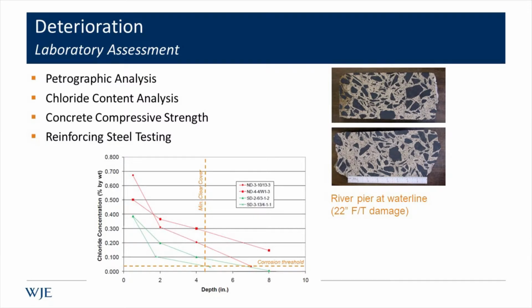That was followed up with a laboratory study where we petrographically examined some of the core samples to better understand the concrete and some of the distress that was present. We did chloride content analysis to figure out what the chloride levels were, and that's just one graph of one subset of cores. But generally what we found was the chloride concentration at the level of the steel was above the corrosion threshold. And that was the case even in areas where there was not distress. Concrete that looks sound and yet has chloride levels that are high enough to promote corrosion. And so that was something we needed to be mindful of as we're designing repairs.